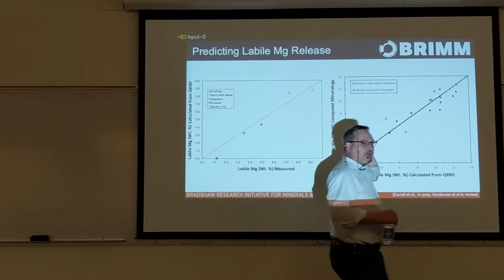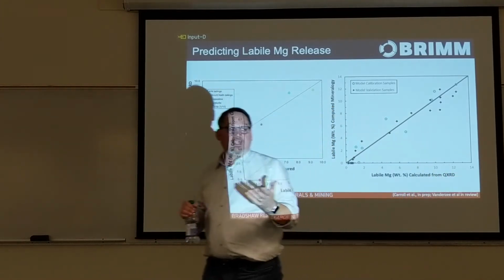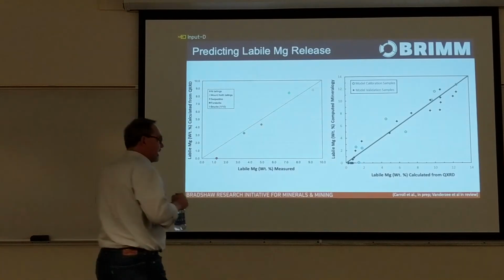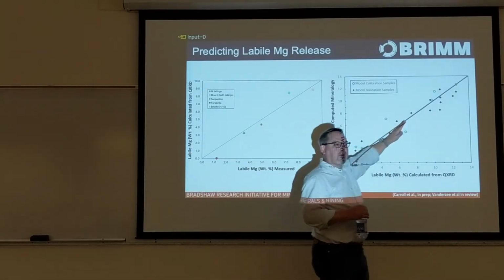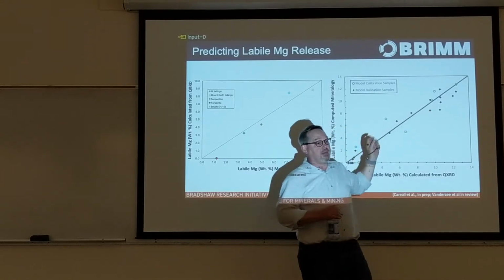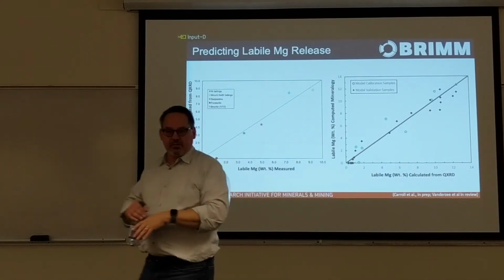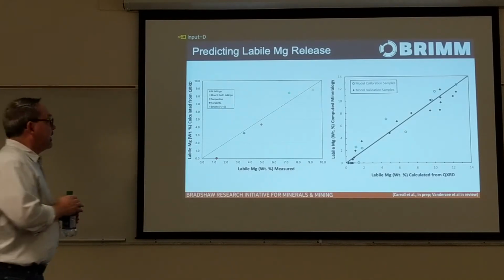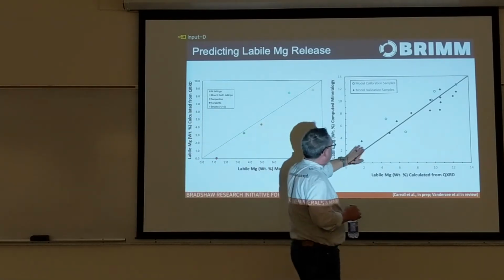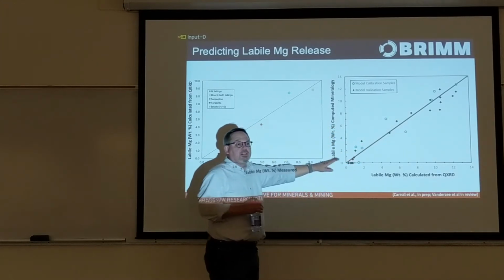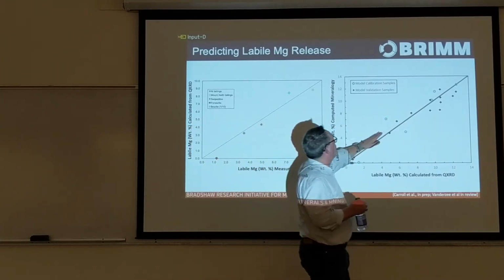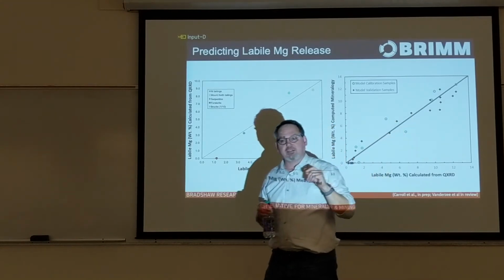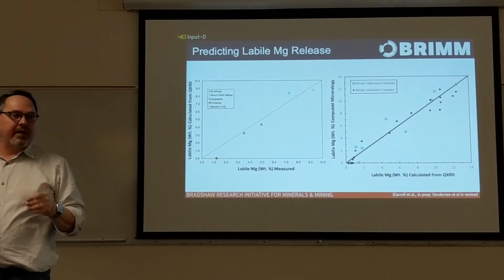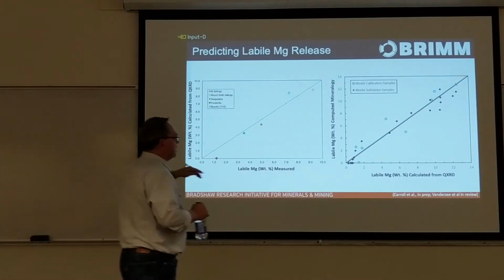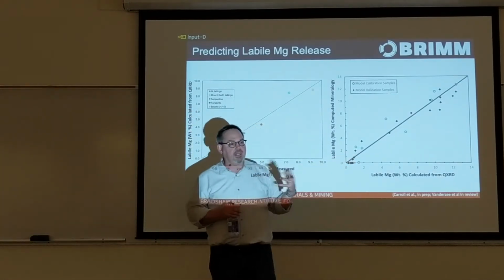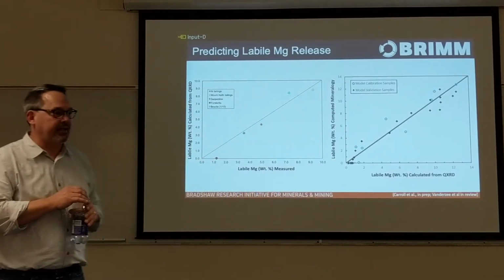Now here we've calculated it from exploration geochemistry from a nickel mine. So we've essentially done a basis transformation and used the bulk magnesium, silicon, loss on ignition, bulk chemical data from a 10,000 sample exploration geochemical database and calculated the labile magnesium from all that exploration data. The blue here were the samples that were used to build the geochemical model, and then there's 20 validation samples. The 20 black dots were 20 additional samples that we ran the model on, but we didn't tune the model to reproduce them. So they're the validation samples: 10 to build the model to calibrate, and 20 to validate.